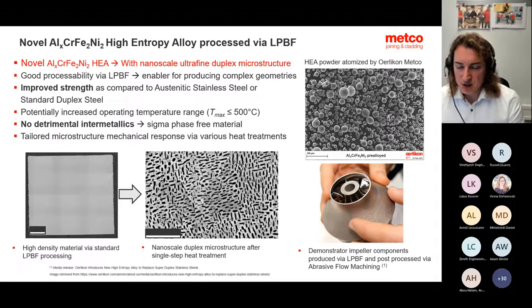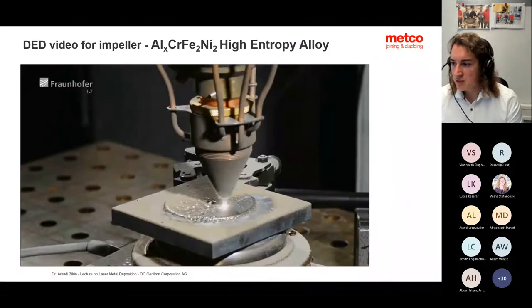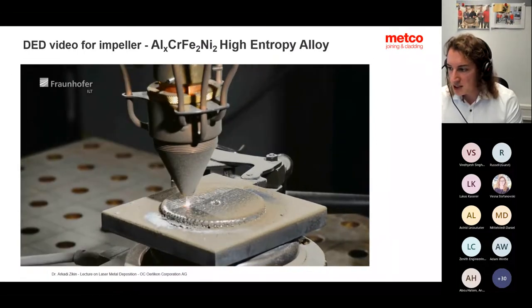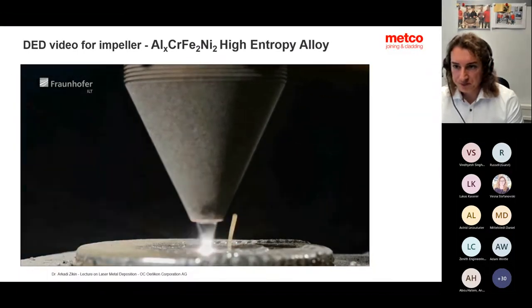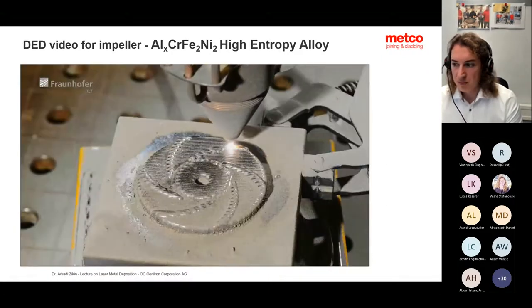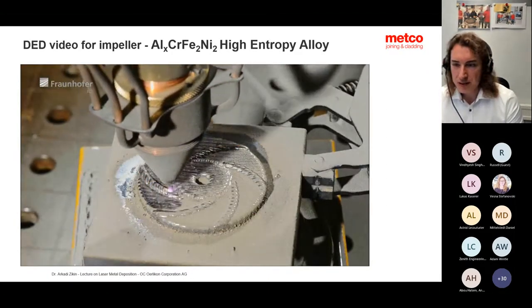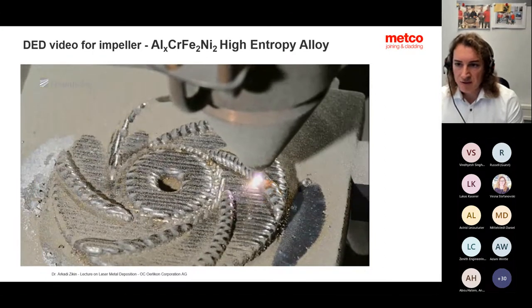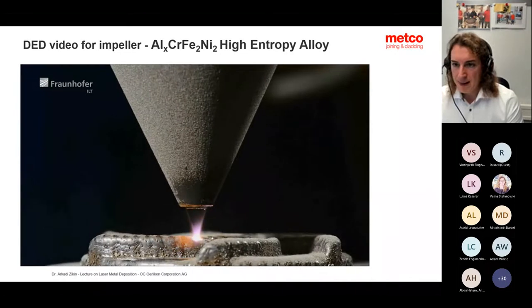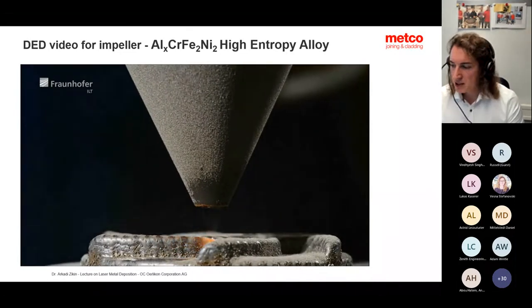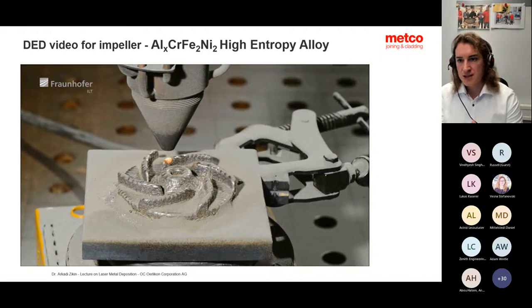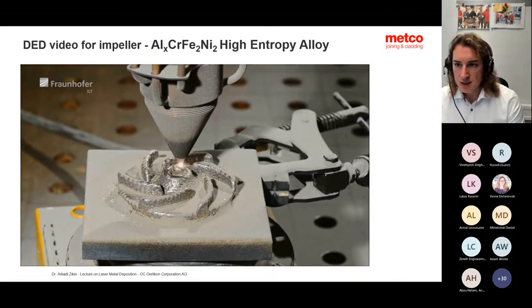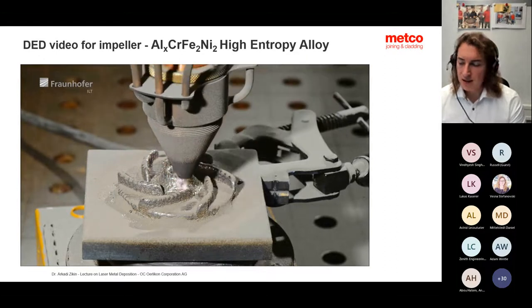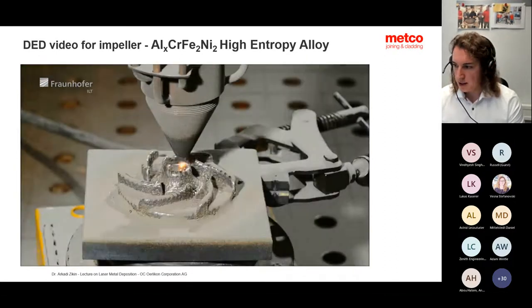And there are a lot of papers in that direction. You would probably contact my friends from additive manufacturing who can tell you more in detail, but most importantly, we tried this alloy also in a DED application, producing complex shaped components, and we see there are no defects in terms of porosity or cracking, very smooth, very beautiful deposition features of this type of material. So in my opinion, working in this direction like high-entropy alloys, we certainly can change the understanding of existing alloys on the market.